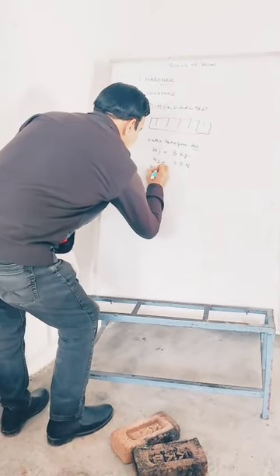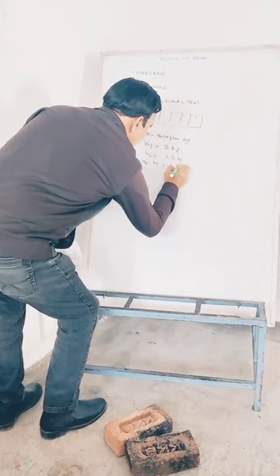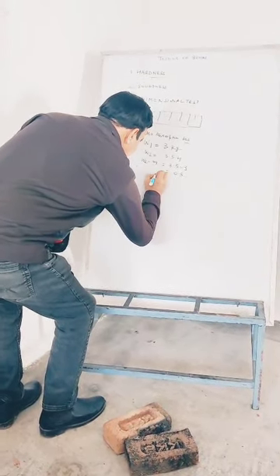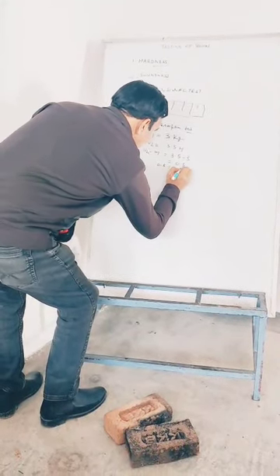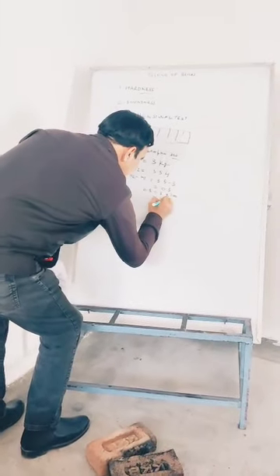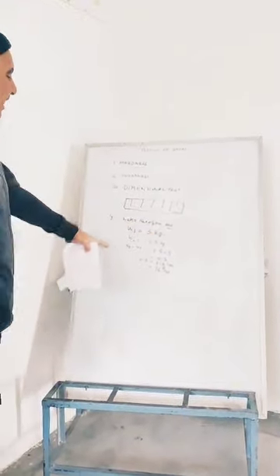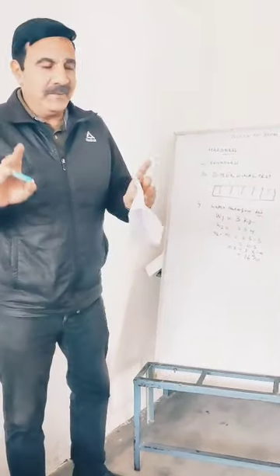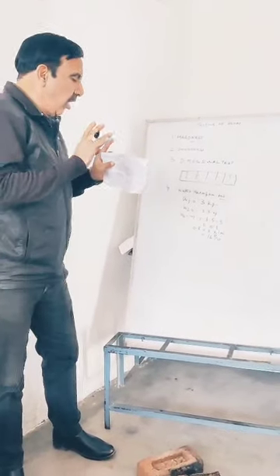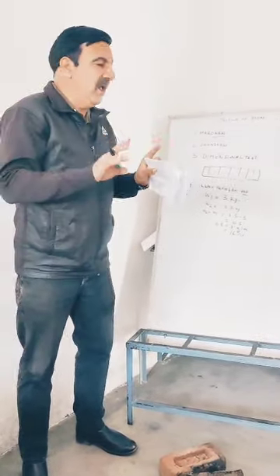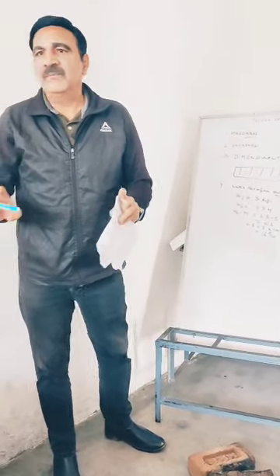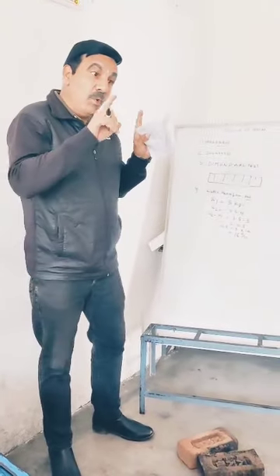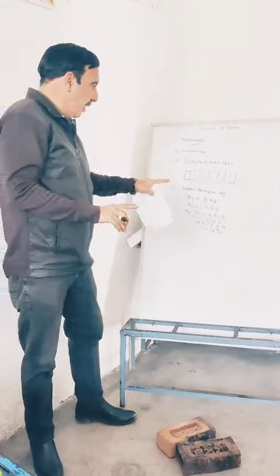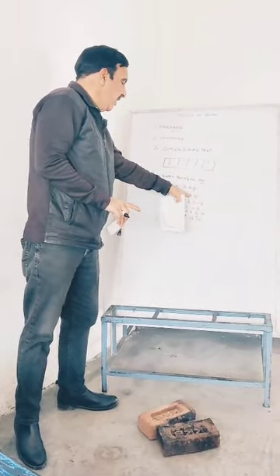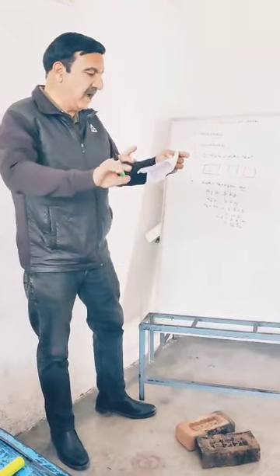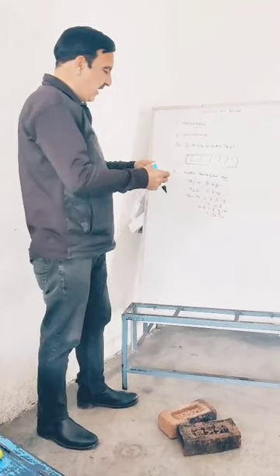So W2 minus W1, 3.5 minus 3 is equal to 0.5. 0.5 divided by 3 into 100 will be percentage. That percentage will be approximately around 16%. So brick absorption test, the tolerance is less than 20%. If bricks are having water absorption less than 20%, bricks are okay, they are approved. If it is more than 20%, then the bricks are not approved. If the weight comes around 4 kg, the tolerance will be more than 20%, the bricks are rejected. Okay, these were the 4 tests we conducted.